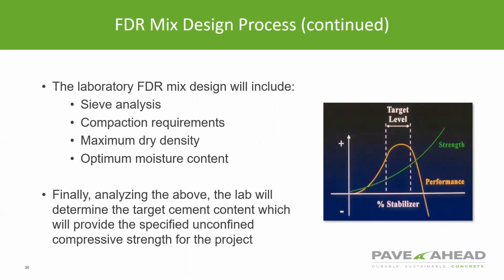It is crucial for you to obtain a good sample of all those materials and that they be combined in the same proportion that you're going to find them in the field. And you want to take enough cores to make sure you have a representative sample for that whole project along the length of that project. And in the lab, they're going to run sieve analysis, compaction requirements, maximum dry density, optimal moisture content. And finally, they'll analyze all of the above, and the lab's going to determine the target cement content, which will provide the specified unconfined compressive strength for the project.